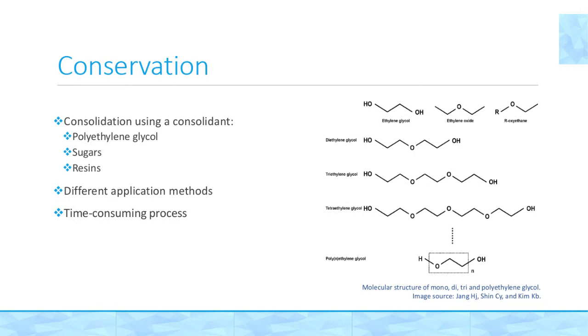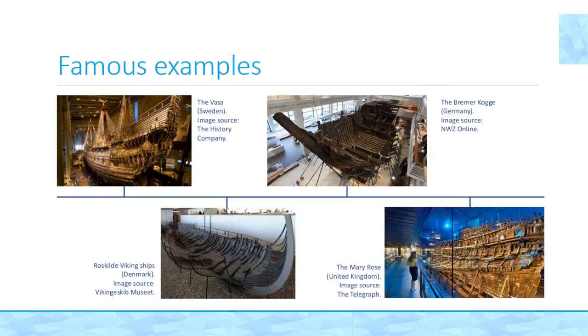Polyethylene glycol isn't the only material that's used for consolidation, though. There are also examples where sugar was used or even resins, but this is generally speaking a little less common. There are different application methods, but in the Netherlands, impregnation by submerging the objects in a basin filled with PEG dissolved in water is the most commonly used method. But the method is rather time consuming and average treatment times take up to 2 years to complete.